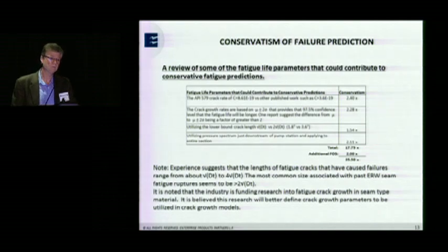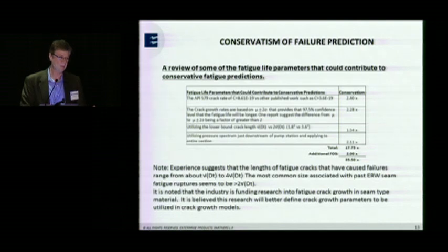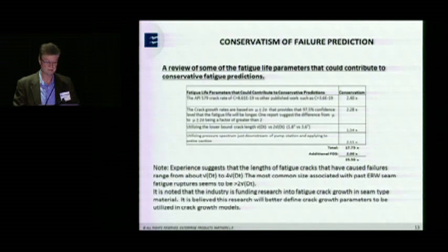And then the other one is what do you use for a crack size? There are some good reports out there that indicate the fatigue cracks that are observed are anywhere from 1 times the square root of dt to 4 times the square root of dt, with 2 times the square root of dt being kind of a good average. And you can see if one uses the lower bound, 1 times the square root of dt, that lower length gives you a greater depth and a shorter life. There's a factor of safety there of 1.4 if I apply it to this.